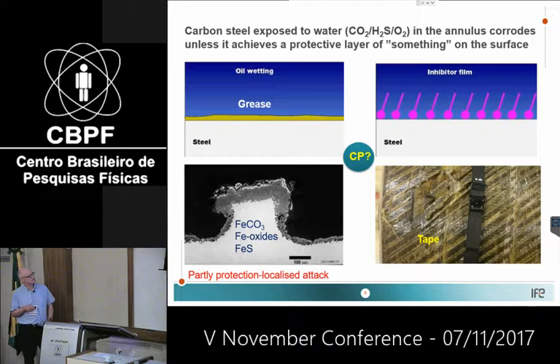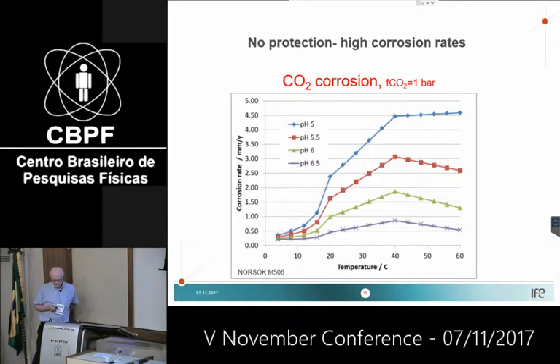This is cross-sections of the steel. And in this case, it protected this column, but not the rest. That corroded fast. And when you have partly protection, you get localized attack, pitting, whatever you call it. And it was mentioned the Norsok model. It was not good enough, Laurie told us. And this is what the Norsok model will predict in such annulus. The pH will increase due to accumulation of corrosion products. But when you reach a reasonably high pH, you still have 0.7 millimeter per year at 40 C at 1 bar CO2. So you need protection. You cannot rely on just non-protected corroding steel.